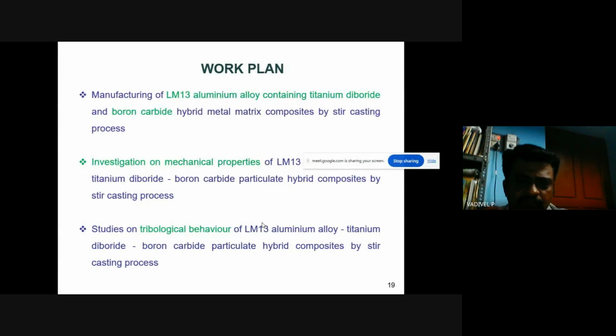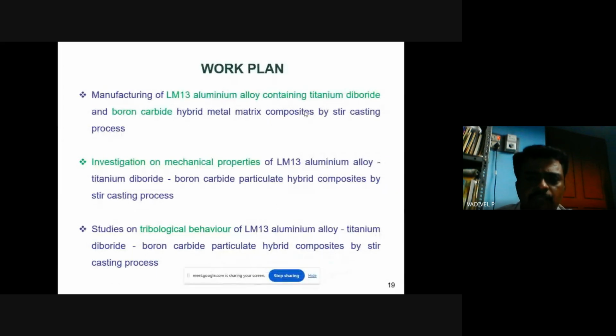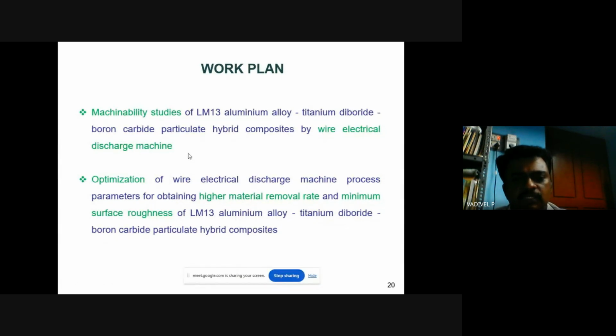So in manufacturing, we have done the aluminum alloy with titanium diboride and boron carbide. We have mixed the aluminum matrix and the composite materials by using the stir casting process, and investigated the mechanical properties of this new hybrid composite, and studied the tribological behavior of the LM13 aluminum alloy with titanium diboride and boron carbide particulate made by stir casting. The machinability studies of the aluminum alloy particulate hybrid composite were done by using wire electrical discharge machining. For optimization, we have done the electrical discharge machining process for higher material removal rate and minimum surface roughness of the LM13 alloy and titanium diboride particulate hybrid composites.